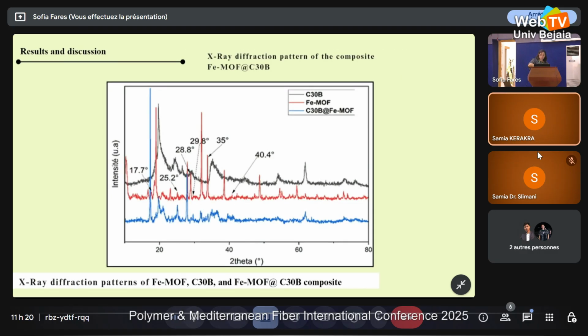X-ray diffraction pattern of the composite: as can be shown in this figure, the MOF exhibits distinct peaks confirming its crystalline structure. And in the composite, the pattern shows the characteristic peaks of the MOF and a broad peak from clay, indicating successful incorporation of the clay in our MOF.